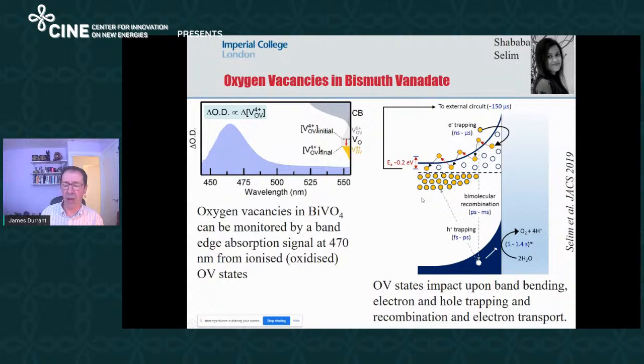And you can just see some examples of timescales of charge trapping and transport, which she's measured in her studies. Of course, these oxygen vacancies in their bulk are mainly occupied by electrons, and that's what makes the system N-type. But in the space charge layer, these oxygen vacancies are largely vacant. They are largely released of their electrons, so oxidized, which is what causes the space charge, which causes the band bending, which means that in the bulk, these states are hole traps because they're full of electrons. On the surface, the same states act as electron traps because they're empty of electrons.